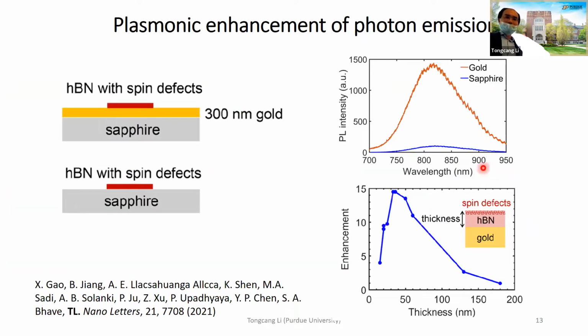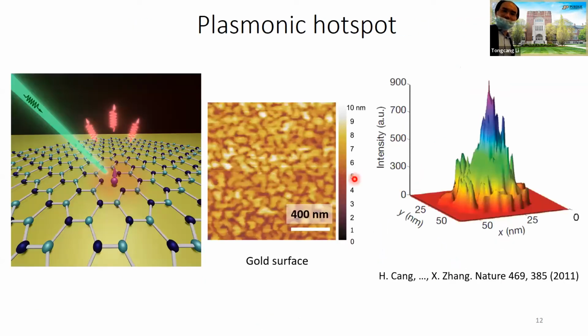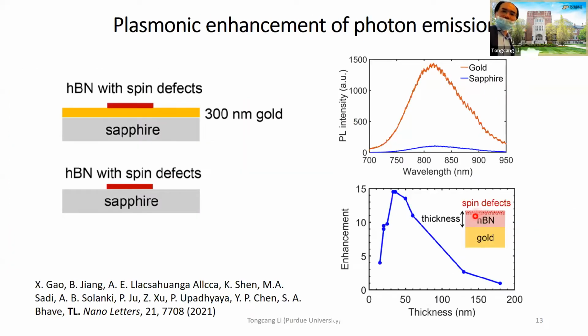So we tried to study plasmonic enhancement. We compare two different cases: hBN on sapphire, which has no plasmonic enhancement, and hBN on gold film on top of a sapphire wafer. We can see the hBN on gold film is about 15 times brighter than the hBN on sapphire. And remember these hot spots have some size scale, on the order of 15 nanometers. To prove this is really due to the hot spots, we also change the thickness.